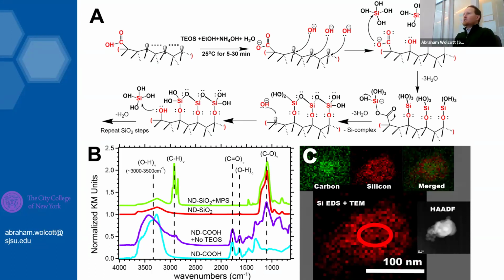So we've got a new look at what a carboxylic acid terminated diamond would look like. We do our acid-base chemistry. You can see right here that we have very few alcohols in our CO stretching mode, and we have mostly carboxylic acids, which are seen at 1780. But if we were to do our silica chemistry without TEOS, these alcohols reemerge. So I believe that we've got a metastable anhydride chain on the surface. These hydroxide ions come in, rehydroxylate the surface, and then are used during this silica chemistry growth.